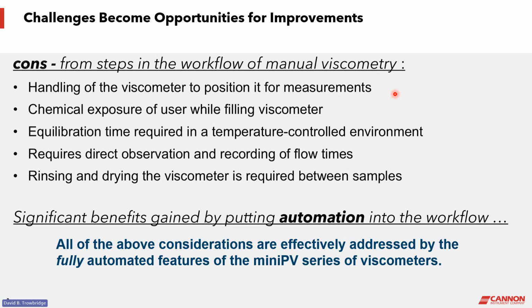It takes time for that material, the sample, to heat to the bath temperature, and then you have to be present to observe the flow and record the flow, and you have to then pull it out, rinse it off, dry it, put the sample in for the next measurement, and put it back in the bath and wait for the equilibration. So very time-consuming and effort-intensive procedure. Fortunately, the automation of the mini PV addresses all of these challenges, these cons, and I'll go over in 2 more slides where those automations come from and how they do this.